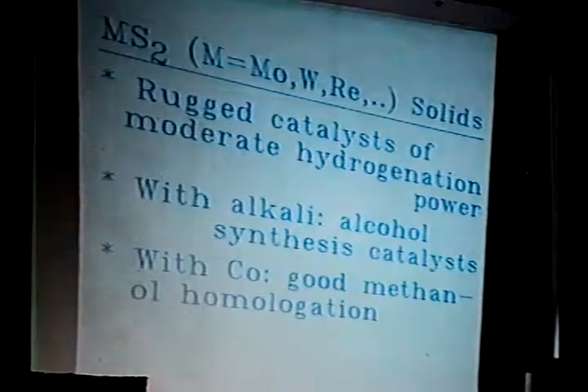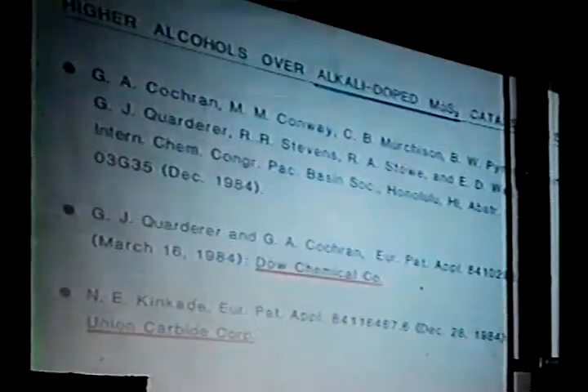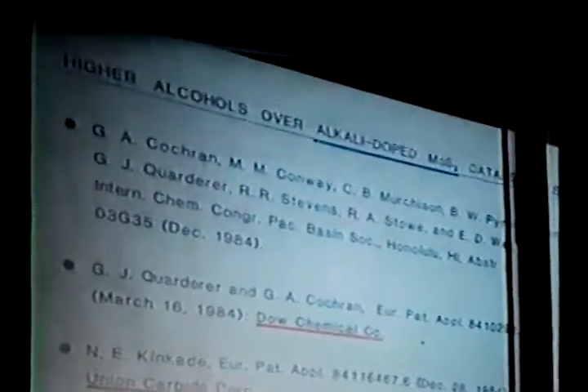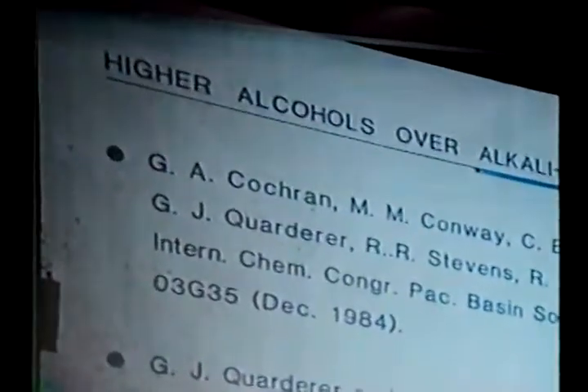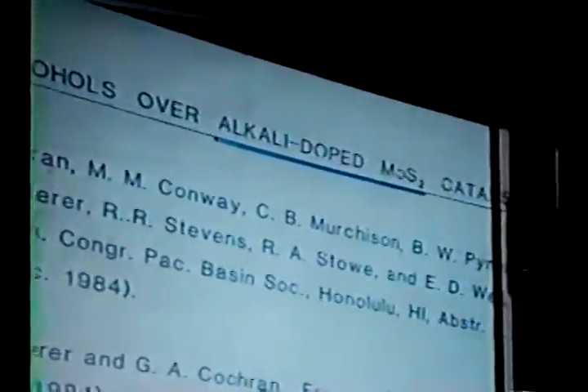And there's a major invention that was announced in 1984 by Dow Chemical Company, that shows that when you dope these catalysts with alkali, instead of having hydrocarbon reactions occurring on them, these catalysts will perform alcohol synthesis. And the alcohol synthesis will be primarily methanol synthesis followed by some chain growth. I quote the invention here in references to Dow Chemical, but also to Union Carbide. In both cases, alkali are essential components as well as molybdenum disulfide of those catalysts.